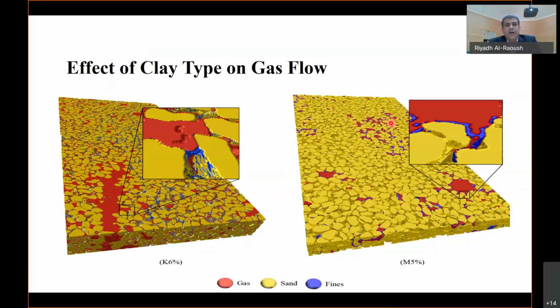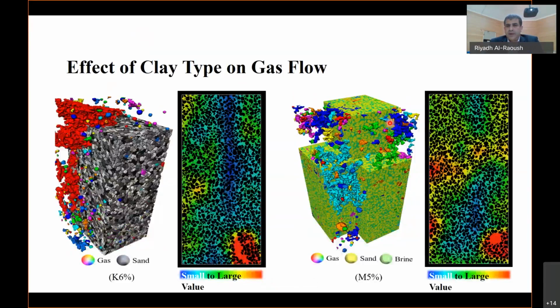This image here shows the impact of the type of clay on the flow of gas in porous media systems. We can see here in this image, kaolinite causes gas to flow as a continuous phase. This one, this red one here. However, in this case here, you can see that another type of clay, which is montmorillonite, causes gas to flow as a disconnected phase, which in turn increases the amount of trapped residual gas phase in the system. You can see that here, every color represents a different gas phase.